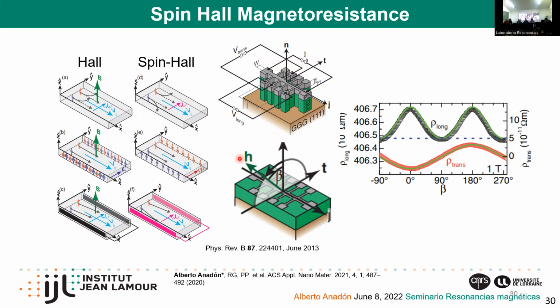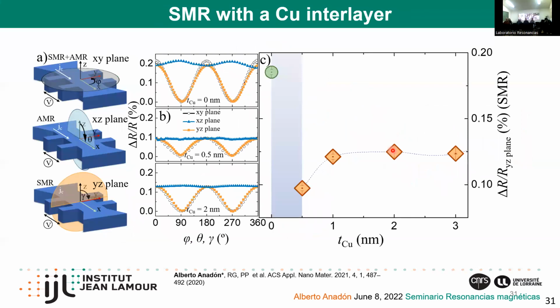So basically, if we apply a current in this direction and we measure in the longitudinal direction, we observe this kind of behavior when we rotate the sample in this plane. Okay, so we studied how this magnetoresistance evolved in our system, and we see a significant decrease of the spin Hall magnetoresistance when we introduce the copper interlayer, and we ascribe this fall of the spin Hall magnetoresistance to an increase of the spin memory loss due to the introduction of copper.